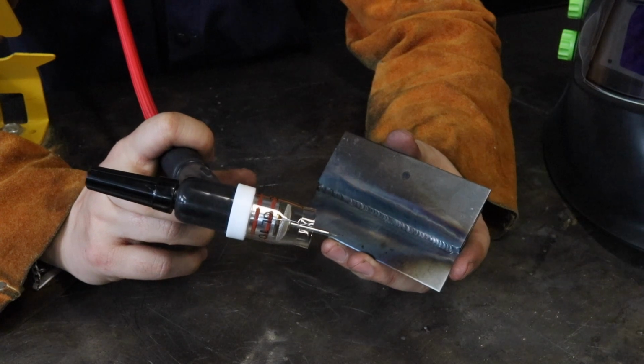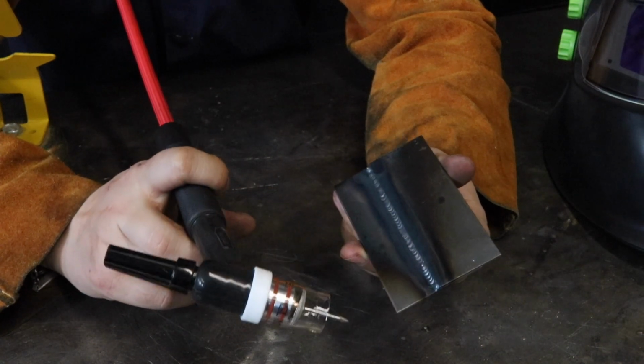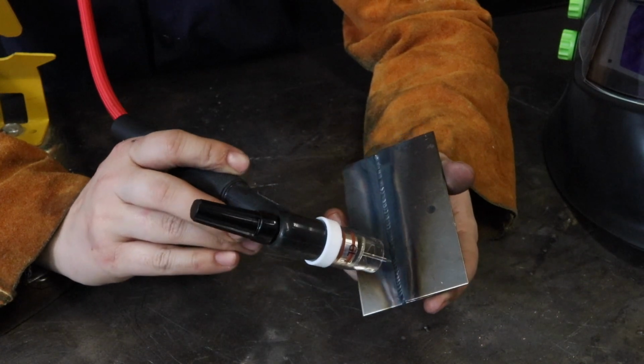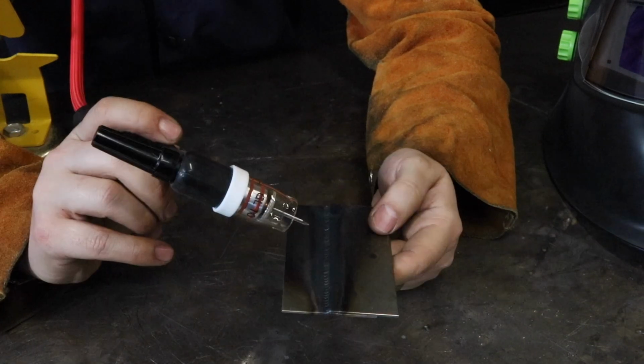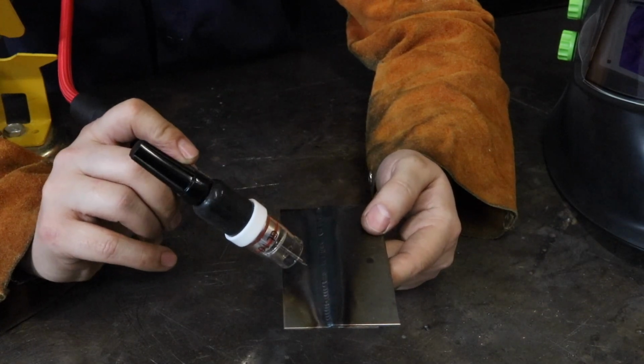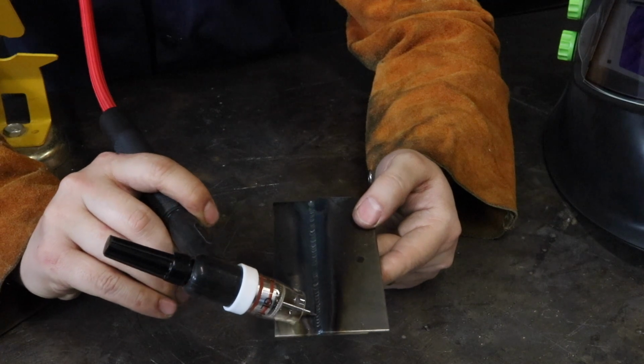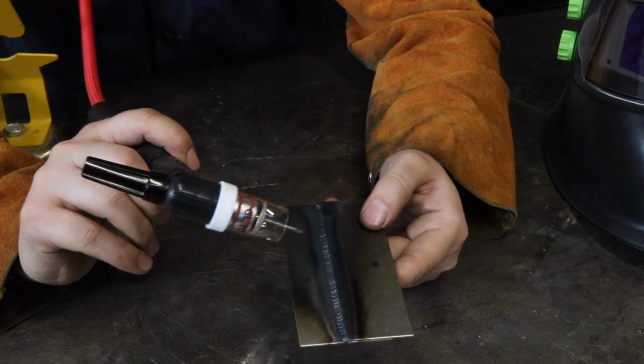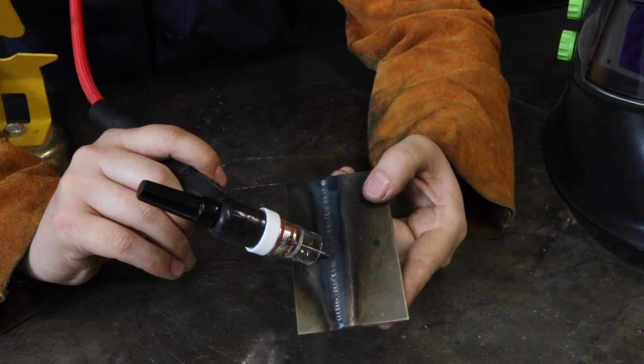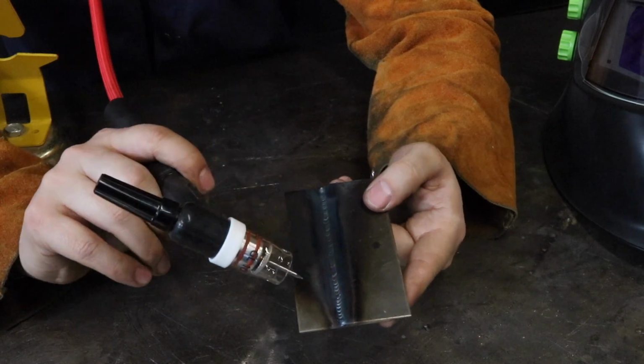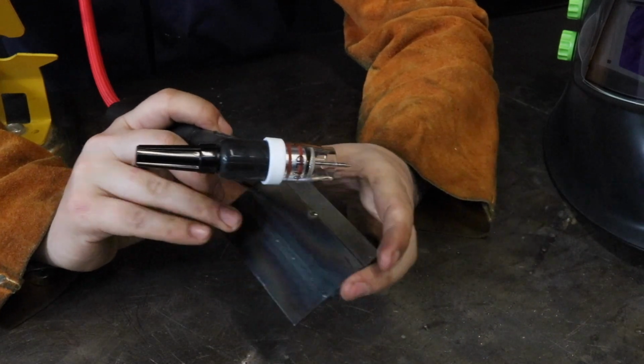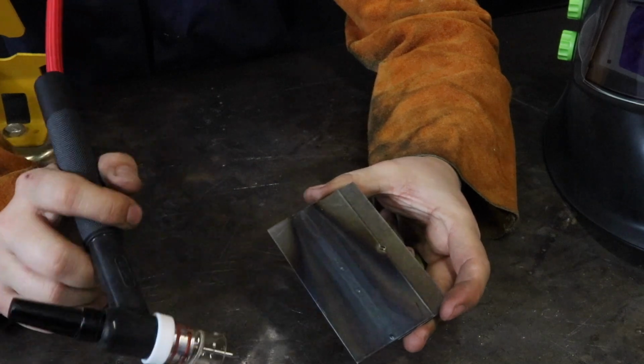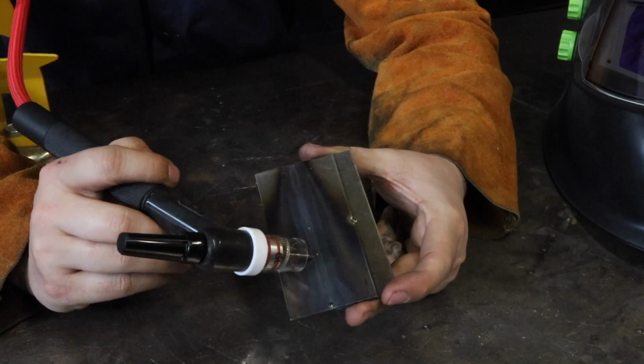We just finished welding 16 gauge carbon steel. The nice thing about this cup again is I was actually able to look through the cup. My heat affected zone is nice and even on both sides. Also, there's no real high or low points in the actual weld. The weld size from side to side was even throughout. One other thing you can notice is, again, the heat affected zone on the back side and very minimal burn through. Looks good.